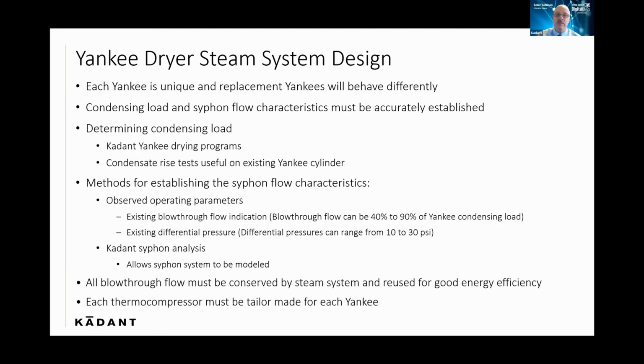Every Yankee is unique. Every Yankee has its own siphoning system. So you can't just take, say, a 4-inch thermal compressor from one Yankee and apply it to another. Likely it's not going to work very well. The first step in determining the operating conditions is the condensing load. If this is an existing Yankee where you're having an issue with the thermal compressor, doing a rate of rise test is the best tool for determining the actual condensing load. You measure your rate of rise, how long it takes for the condensate to go up a certain height in that separator tank.